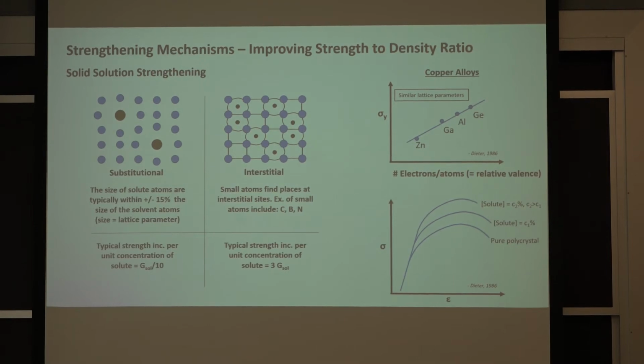Some other factors that affect the strength of a solid solution strengthened material are how much solute material you're putting in there. More solute gives you an increase in strength, as you can see from the bottom graph. Another thing that increases the strength is the valence state of the material that you're putting in there, the solute material. If you have a large number of electrons per atom, the strength actually goes up even for a similar lattice spacing. And that you can see in the top graph.